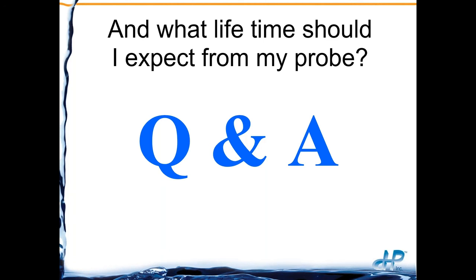Ready? And what lifetime should I expect from my probe? This is a hard one to answer because I need to know more about the application. What's the temperature? What's in there? So if you're just in an effluent wastewater, you should be getting at least 12 to 18 months out of your probe. But if you're in a CIP application that is running all the time at 130 degrees C, you're going to get very short life out of it.